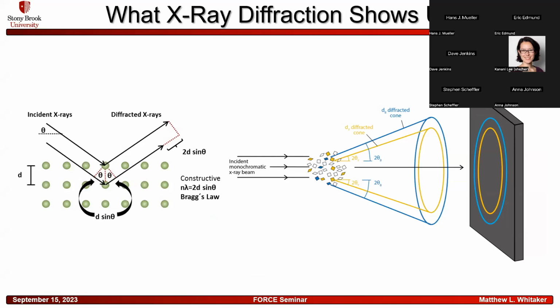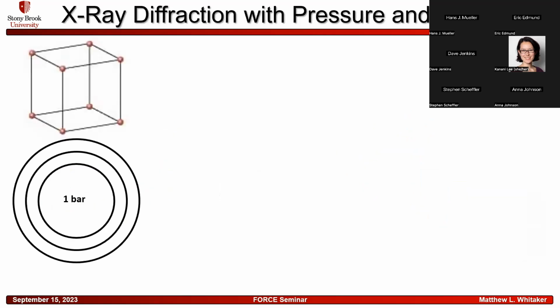We have the incident X-ray beam coming in and hitting the sample, and the X-rays are then scattered off of the atoms in the crystals in that sample. And when they're scattered constructively, that's what will form the peaks that we see in normal diffraction patterns. Since we're randomly orienting the crystals in the sample and we're doing a full two-dimensional diffraction pattern, those peaks end up showing up as rings on our detector, which is shown at the right.